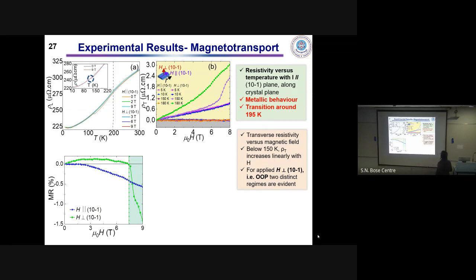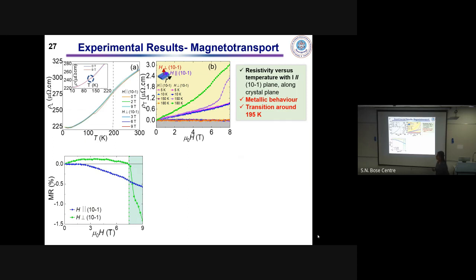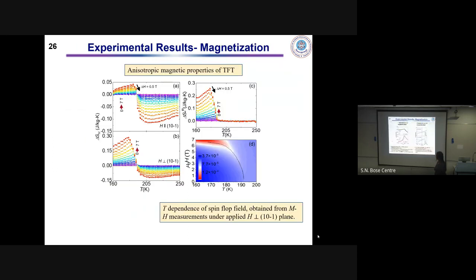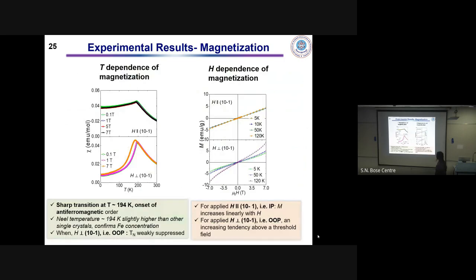And from the transverse resistivity versus magnetic field... But here you should see that in the magnetization measurement. We don't have any data in 9 Tesla. We could measure till 7 Tesla. But corresponding to that temperature, there is nothing in your magnetization. There should be something. If you are claiming it to be spin flop, it should be more evident in magnetization data, especially here.